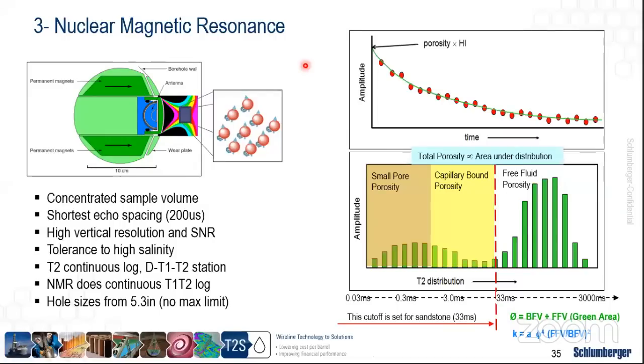Then we have a pulsed magnetic field that's also emitted from the tool, and this flips the hydrogen index from the vertical axis to the horizontal axis. The time the hydrogen takes to go from the horizontal axis all the way back to the vertical axis represents what we call the NMR measurement, which is the relaxation time. By measuring this relaxation time, we measure how much amplitude is coming back to the tool and the time it takes. Typically, the more hydrogen we have inside the reservoir, the higher the amplitude and the longer the time; the less hydrogen index, the lower the amplitude and the shorter the time.